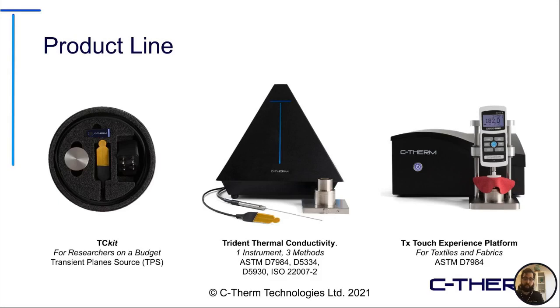Our premium platform is the Trident thermal conductivity platform. In the middle, we have our pyramid-shaped Trident platform. This allows you to drive the multiple methods that I mentioned in measuring thermal conductivity and also thermal effusivity, which we'll be speaking most about today in understanding warm feel and cool touch. Here you have a needle probe for measuring polymer melts or large particle gravel, soil. You have the ISO 22007-2, which can provide some nice complements for things like thin films or testing polymer materials or porous ceramics. And then, of course, the MTPS, Modified Transient Plane Source technique, which is a single-sided measurement and allows us to take effusivity measurements of textiles, fabrics, and lots of different materials.